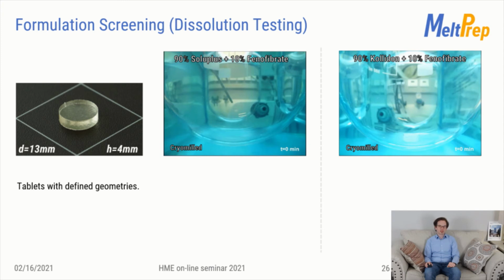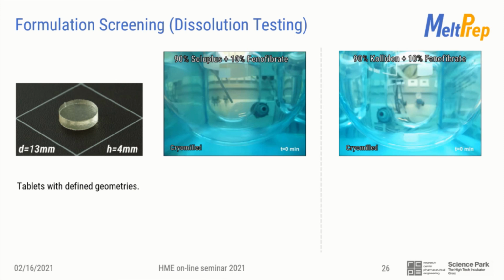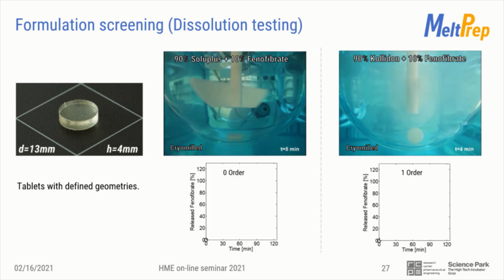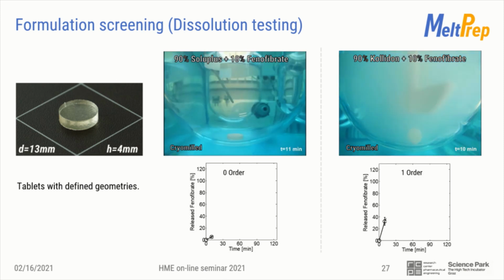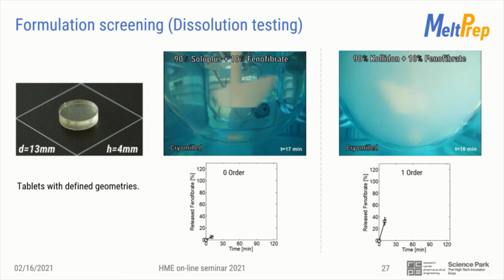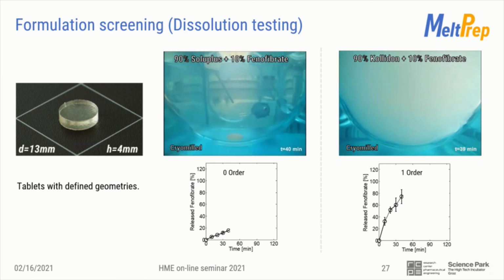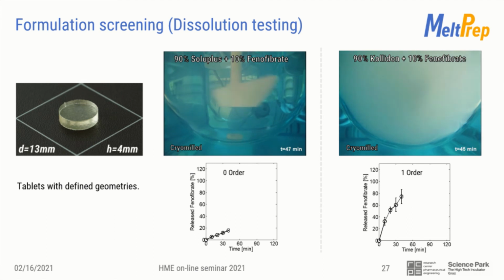You can immediately see in this time lapse here that the fenofibrate tablet on the right side is dissolving super quickly, whereas on the other side the tablet is still intact, just lying at the bottom of the dissolution vessel and dissolving very slowly, swelling a bit and then eroding. This is also the explanation for the difference in the dissolution profile that we see.